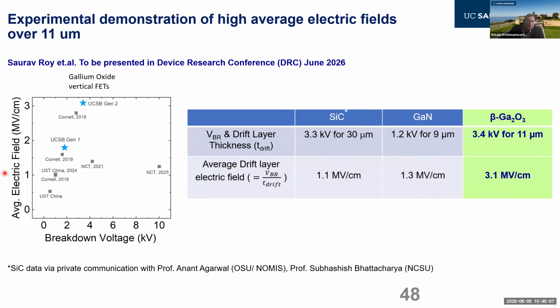So I've plotted this average electric field as a function of the actual breakdown voltage. Normally, lots of groups report excellent high average fields at low gate-drain distance in a lateral device or a low thickness epi in a vertical device. But scaling that to higher voltages is generally challenging. But here we've been able to simultaneously get high breakdown fields at high breakdown voltages. And these are some record results right now, to be presented later this month at DRC.